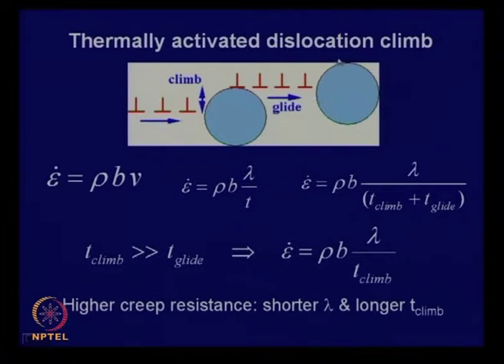That means if you make this particle bigger, it will take a longer time to climb, and always t climb is much larger than t glide. So, you can approximate the expression like this. What it means is that for higher creep resistance you have shorter interparticle spacing and larger particles. So, that is the key.